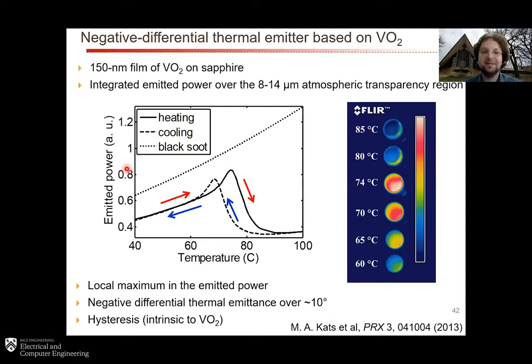But nevertheless, here is a thin film of VO2 on a sapphire substrate, and you can see that the emitted power, instead of increasing gradually as a function of temperature, as you would expect for a black body or a typical surface, reaches a local maximum, and then has this sharp decrease, which is very, very strange. It means that when you point an infrared camera at this object, at 60 degrees, it looks kind of cooler, at 75 degrees, it looks hotter, and at 85 degrees, it looks colder than it did at 60 degrees, even though, of course, it's actually quite a bit hotter. And that's a result of this negative differential region over here.